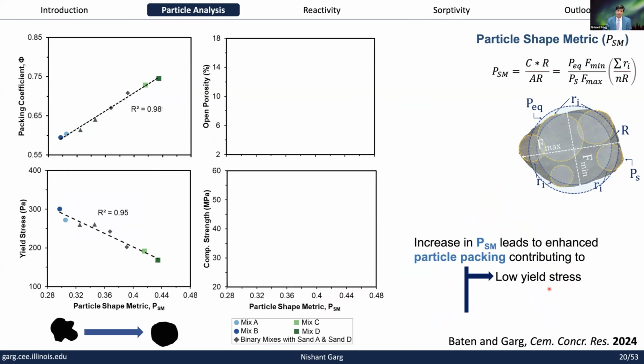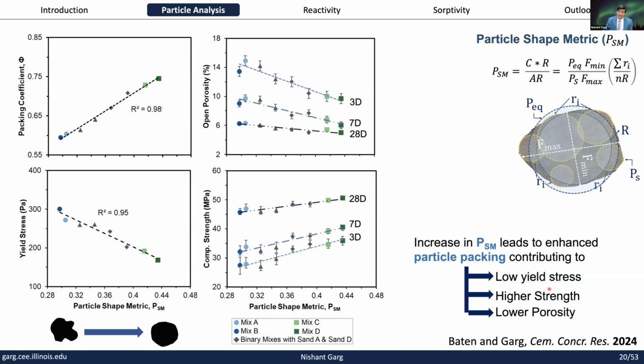And it turns out this particle shape metric is actually very well correlated to many different things which we care about in mortar and concrete, all the way from packing coefficient, which comes out independently from helium pycnometry, as well as yield stress, which tells us about workability, as well as the strength and the open porosity. So in general, our key message here is that size is very important, but the shape also matters. And now there is a way to encapsulate that shape into a single metric.